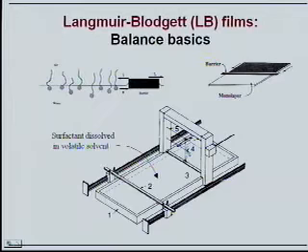And the final experimental problem that you have is that if you drop, let's say, your lipid as a small chunk of lipid, it may not spread fast and evenly. So for this reason you take the surfactant, dissolve it in volatile solvent, drop a droplet of the solvent on the surface, the solvent evaporates, the surfactant spreads out, and you have this monolayer which you can compress with the barriers, and which you can transfer to solid surfaces, as we're going to discuss a little bit later on.